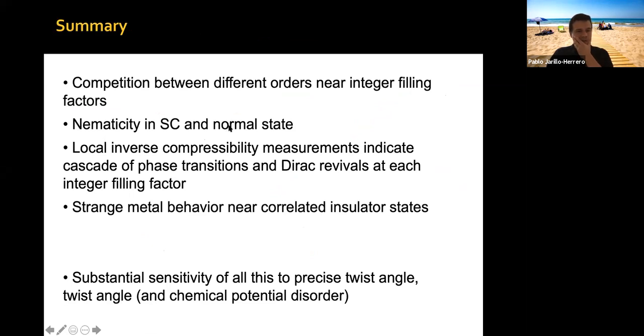So let me leave you with the summary. In this system, as in many correlated materials, there is a competition between different orders. This depends on your twist angle, which controls the interaction energy scale over the bandwidth. It also depends on parameters like disorder, and on the density you are filling. There is nematicity, in particular anisotropies, both in the superconducting state and in the normal state, and they seem to be of independent origins, but they coexist in some regions of the phase diagram and affect each other. And these local inverse compressibility measurements indicate a cascade of phase transitions and Dirac revivals at each integer filling factor.